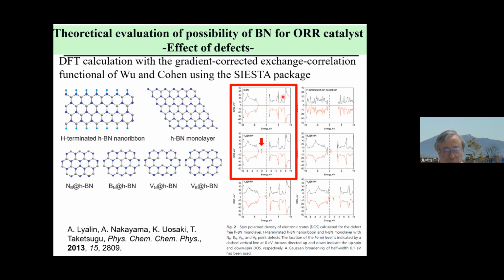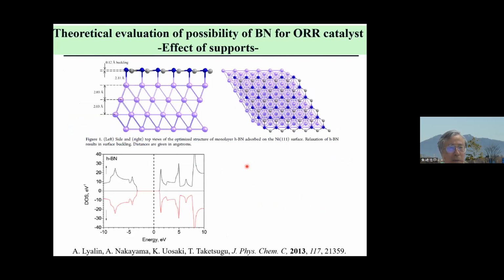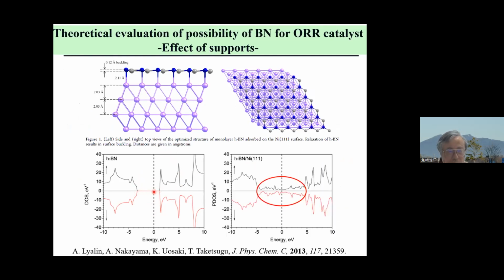In the case of some defects, we found that some intergap states are introduced, but a more drastic effect was observed when the boron nitride is placed on a surface or on a support. This is a calculation of boron nitride on nickel 111. This is the boron nitride itself. There's a huge energy gap, but once it is placed on nickel 111, there are lots of residual states within the gap. So there's a possibility that it can be more electronically conductive.